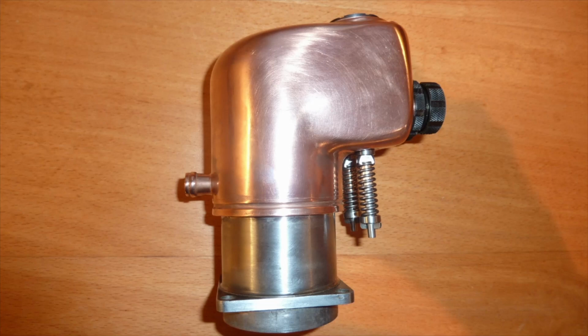I discovered later that unless you plan to heat the article for something like silver soldering, adhesion is good enough. But if you plan to heat it up to brazing temperature, the top layer of plate may well blister away from lower layers, which would be disastrous.